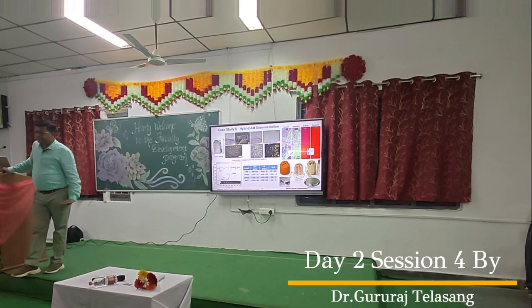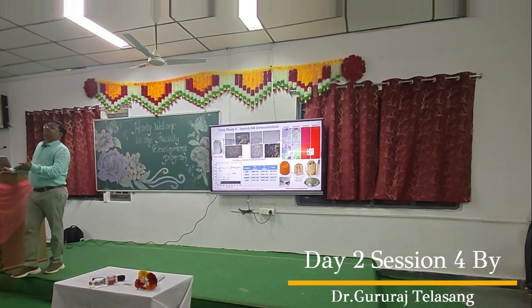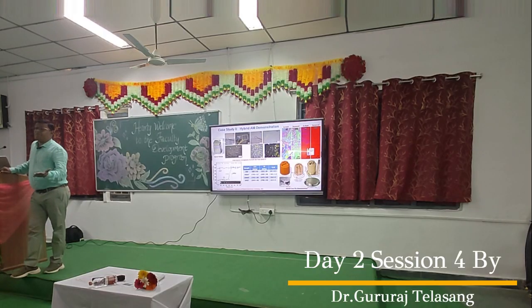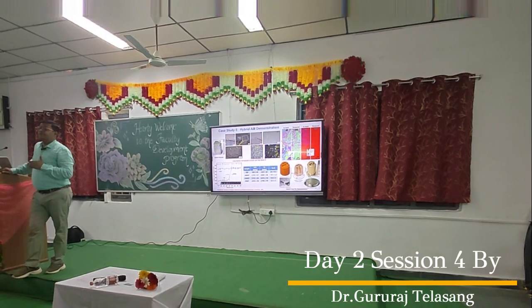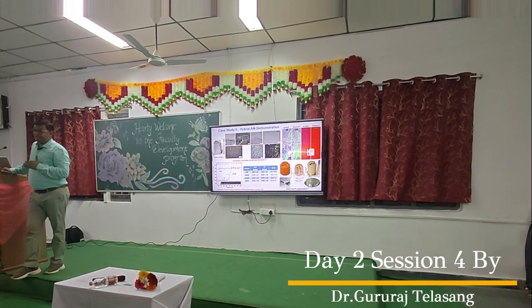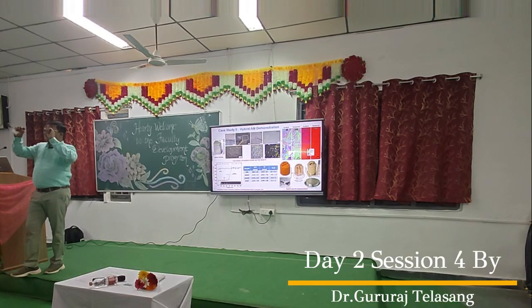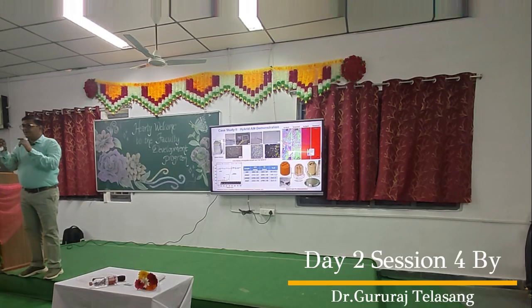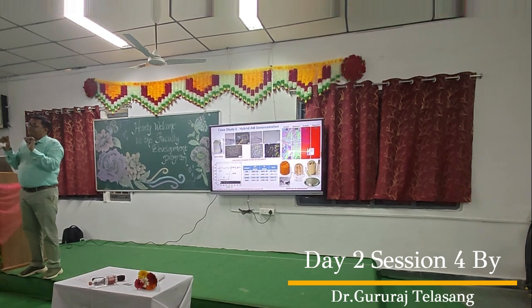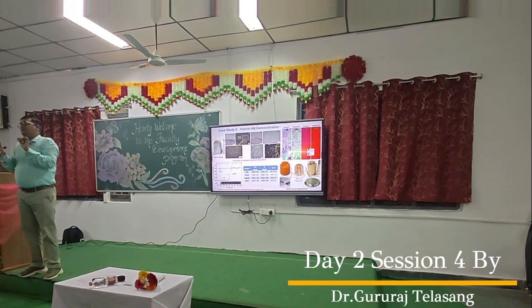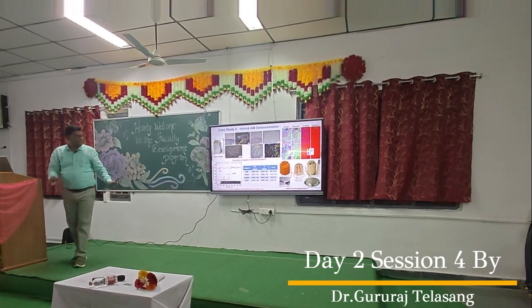Yes, there is a problem, but where is the problem? The problem is away from the solidification, the aluminum melt solidification. I told you I have a solid bed and I have only 10 to 20 mm which is exposed to the aluminum melt. I am 20 mm away from that exposure. So these kinds of properties could be okay there, but not on the surface, but far away from the aluminum solidification should be okay. But this has to be proven.